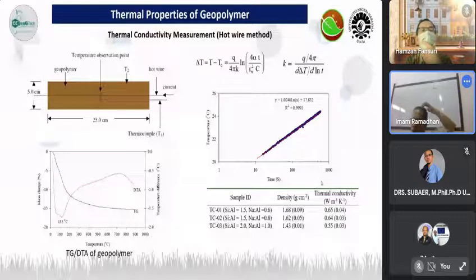But when I did my PhD, I made a sample with a length of 25 centimeters and a diameter of 5 centimeters, and embedded the wire in the middle of the sample. With a special design of the mold, I could insert the tip of the thermocouple. One was inserted in the middle of the wire, and the second you can put a few millimeters from the wire. So it's a very challenging task to produce this sample.